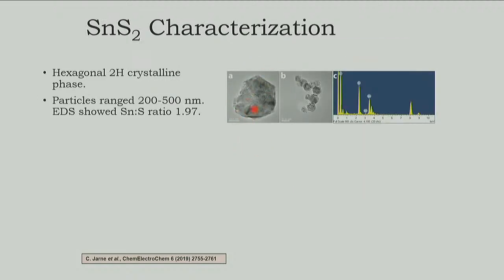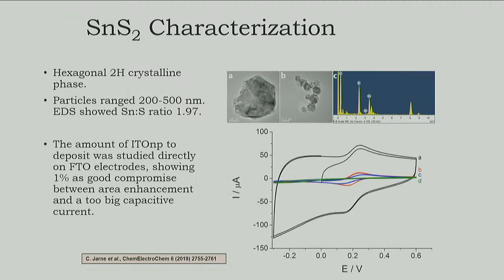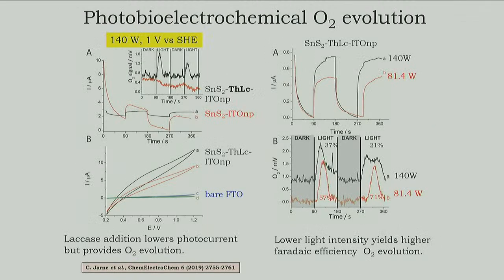This is how the particles look. You see, like 500 nanometers, they have this hexagonal shape. And when we put the ITO nanoparticles, we can see that we go from 0.01% increasing in 1 order of magnitude until 10%. This is very big, so capacitive current here is going to mask everything. So we decide to stay at 1% concentration when depositing the particles, which made a good increase. So this is the response we got here.